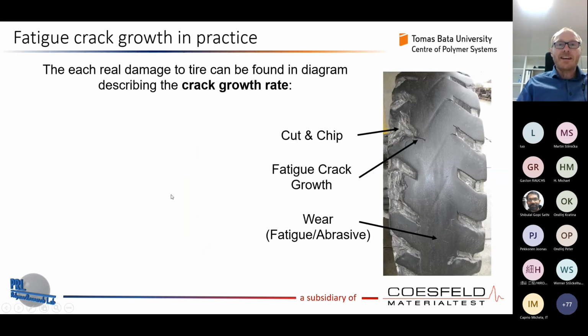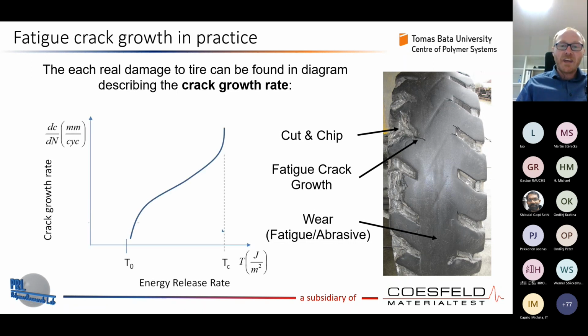So, and now fatigue crack growth in practice. This was slightly the theory, as proved with laboratory methods. And what is it in practice? Here we have an example of a tyre, and in a tyre we can find, let's say, every fracture process. There is wear, fatigue wear or abrasive wear. We have fatigue crack growth visible here. We have cut and chip here. And how this is associated with that fatigue crack growth characteristic we have here.